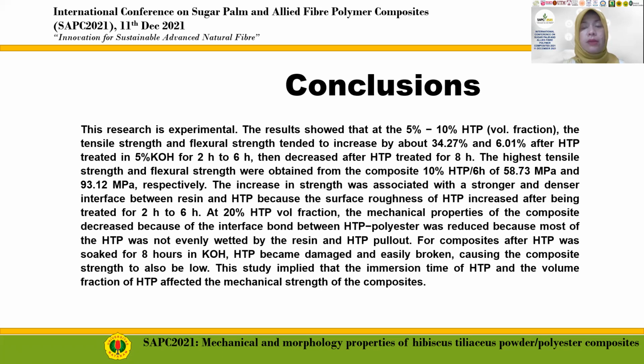For the composite after the powder was soaked for 8 hours in potassium hydroxide, the powder became damaged and easily broken, causing the composite strength to also be low. This study implied that the immersion time of the powder and the volume percent of the powder affected the mechanical strength of the composite.